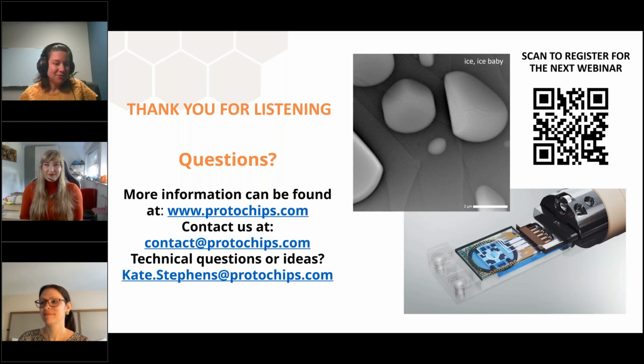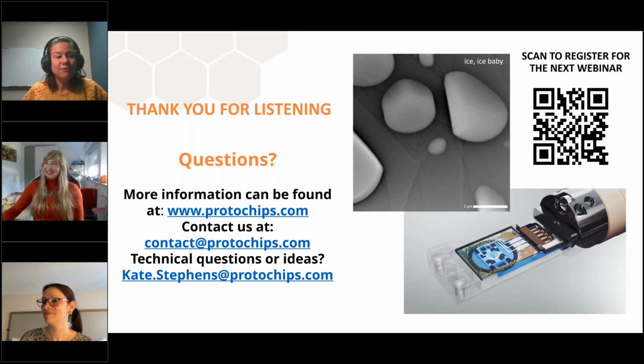Before I did any freezing inside the microscope, I did a whole lot of freezing inside of our pumping station to make sure that I wasn't going to damage my microscope. Not as worried about the cell as I am about my microscope, well, NC State's microscope. But yes, you certainly can if you're not careful. And that's actually why we limit the rate at which you can cool and the rate at which you can heat.